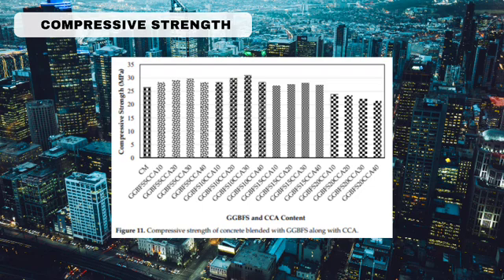Also, the compressive strength depicts the concrete with the accumulation of 5 to 20% GGBFS by weight of PC along with 10 up to 40% of CCA as a sand replacement, to analyze the effect of PC and FA replacement on the compressive strength of concrete. The greatest value of compressive strength is 31 MPa with 10% GGBFS as the PC replacement along with 30% CCA as a FA replacement, and the lowest value is 21.18 MPa with 20% GGBFS and 40% CCA together in the mixture of concrete at 28 days. The compressive strength is heightened at levels of GGBFS up to 10% and CCA up to 30% in the concrete mixture at 28 days.